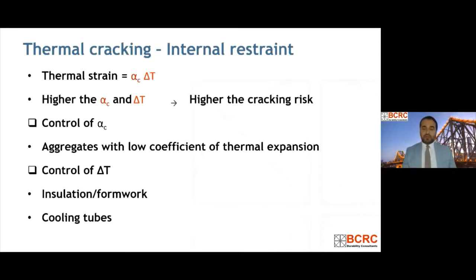So to eliminate the risk of cracking, we need to lower these two factors. We need to select the right type of aggregates which have a lower coefficient of thermal expansion, so we can get a lower coefficient of thermal expansion for the concrete. That is one way, and the other is to control the temperature differentials. How do we control the temperature differentials? We can do it in two ways: we can use insulation or formwork, or we can use cooling tubes. Let's have a look at an example of controlling the temperature differential by these two different methods.